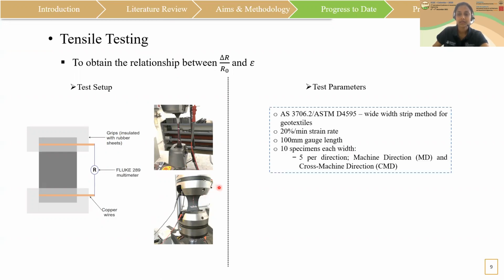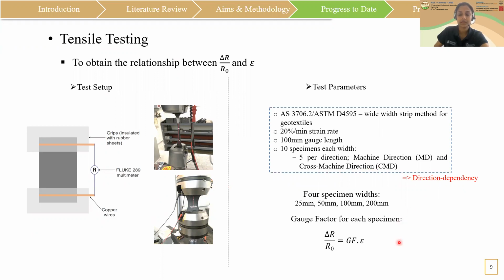The parameters for the standard test, the wide width tensile test for geotextiles, were used, and samples of both machine direction and cross machine direction were tested to find if there is any direction dependency in the electrical behavior. Four specimen sizes were used to see the effect of size on the resistance variation, and the obtained data was fitted into a linear curve to calculate the slope, also known as the gauge factor, for each specimen.